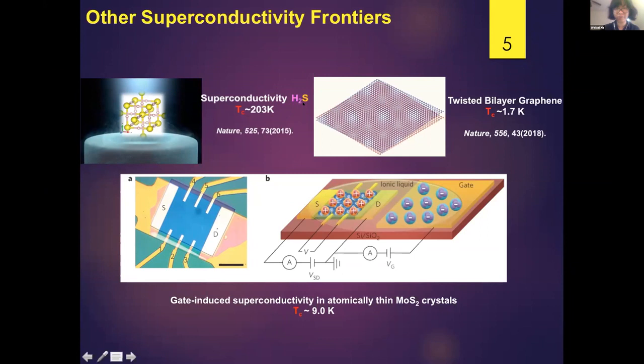So if we press the sulfur hydride to a very high pressure, like 155 GPa, we can see superconductivity at around 200 Kelvin. Okay. And then recently, around 3 years ago, Professor Pablo's group at MIT found out that if you just twist graphene by a very tiny angle, you can get superconductivity, and they observed superconductivity at 1.7 Kelvin.